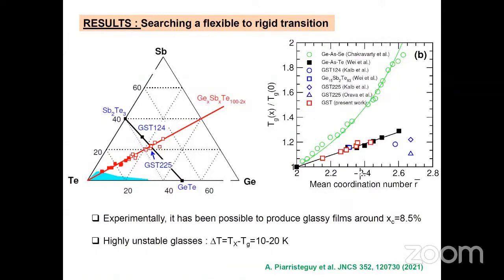So having identified this, let's say, magic composition in this ternary, we have been wondering if we are able to produce glasses, because one of the interesting points of this isostatic stability criterion is that usually you form glasses more easily around that composition. And so one expects to produce glasses in this GST triangle, which is known to have a very, very high crystallization tendency. And so we did this. This is a work in collaboration with colleagues from Montpellier. And so we generated from co-evaporation techniques a certain number of samples along that line.